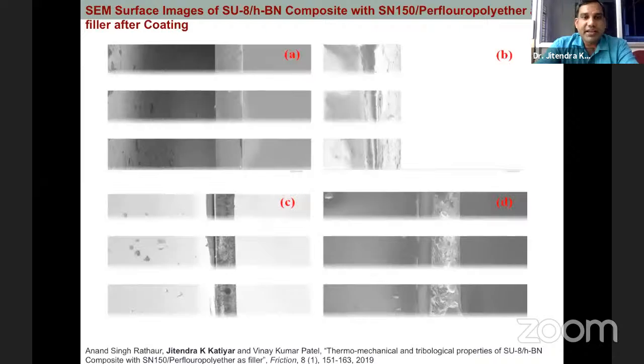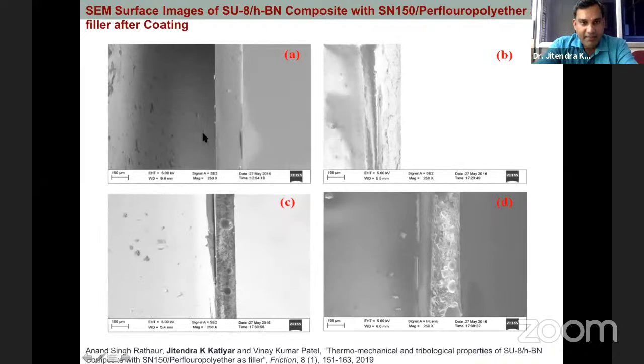I have taken a few sample surfaces of SU8 and its composite coating over a glass surface, a bulk coating which I fabricated to develop some MEMS devices. This is work carried out by my PhD student, who recently submitted his thesis, and this work was published in the Friction journal. Here you can see the surface coating, this is the substrate and this is the coating, through which I can measure the thickness of the surface coating.